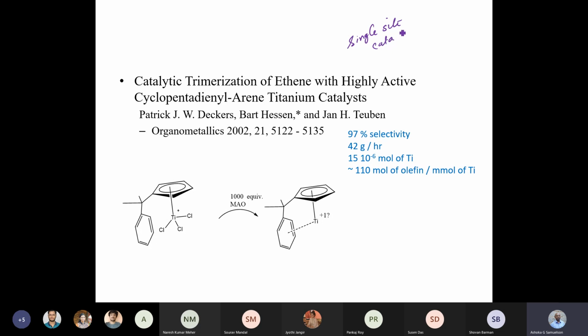So what happens in a heterogeneous catalyst is that the catalyst has got multiple sites, and the selectivity of each site is slightly different from the other. Like for example, there can be steps involved in a crystal lattice, there can be edge defects, there can be corners of a cube. So there can be different types of active sites, this can be the active site as a step. And so it's important to have a single site catalyst so that you can understand and also have better selectivity for a single type of reaction.